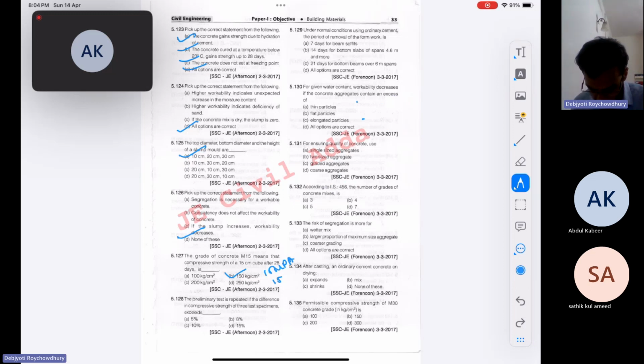Preliminary test is repeated if the difference in compressive strength of the three test specimens exceeds 5%, 8%, 10%, 15%. As per clause 15.4, what does it say? It says that the test result of the sample shall be the average of the strength of the test specimens. The individual variation should not be more than plus minus 15% of the average. If more, the test results of the specimen are invalid, so you have to repeat this test again. So it's 15%.